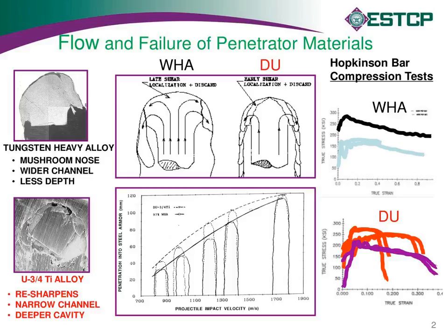The conventional tungsten heavy alloys essentially are too stable under high rate plastic deformation. They build up and support a large mushroomed head. That's why they make a bigger diameter tunnel, whereas the depleted uranium projectiles very quickly go plastically unstable. They start softening with strain more rapidly than they are work hardening with strain. So that leads to a situation where any kind of stress concentration leads to a locally soft region, which is an adiabatic shear band. The material fails along that plane where the adiabatic shear band develops, so it discards deforming material more rapidly. It's sort of a resharpening kind of effect.